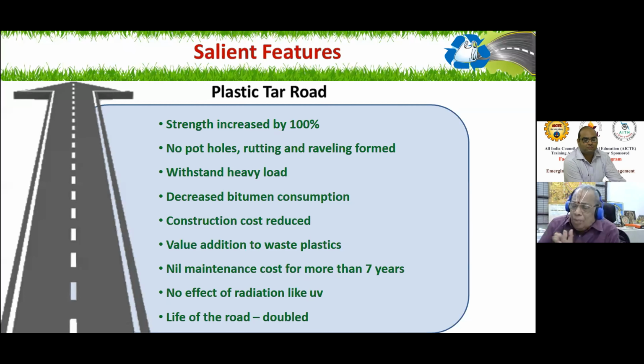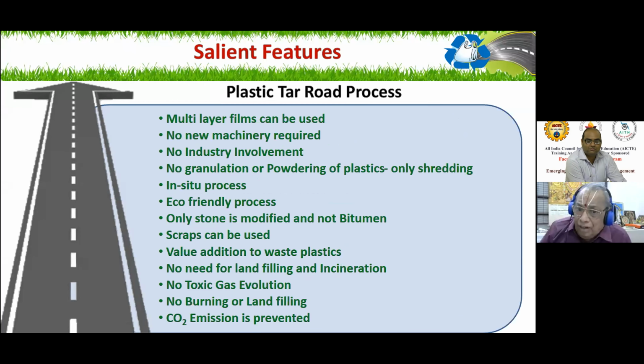And the bitumen and plastic automatically get diffused together and never come out. There is no question of getting microplastics here. So that problem is also solved. And what about the road? The plastic, multi-layer films, no machinery is required, no industry involved, in situ plastic. Wherever you are, collect the plastic, cut it and then lay it. Economically friendly. Only the stone is modified, not the bitumen. And the road that you already laid, you take the scrap out and coat it with the plastic, at 50% cost. The road level height is not raised, the quality of the road is improved, cost-wise 50% only. For a 1 kilometer stretch, 20 lakhs, now only 10 lakhs. So scrap can be used, value addition.